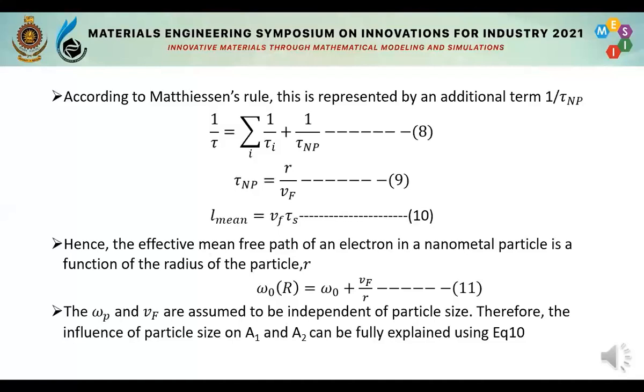In a nanoparticle, the mean free path of conduction electrons is reduced due to collision of electrons with the particle surface. So according to Matthiessen's rule, the total frequency can be described as mentioned. And this is represented by an additional term, the static collision time of the nanoparticle. It can be described by using the radius and Fermi velocity. So we can say the effective mean free path of an electron in a nanometal particle is a function of the radius of the particle. Then the nanoparticle's optical constant becomes a function of the particle size. It is fully explained as mentioned.